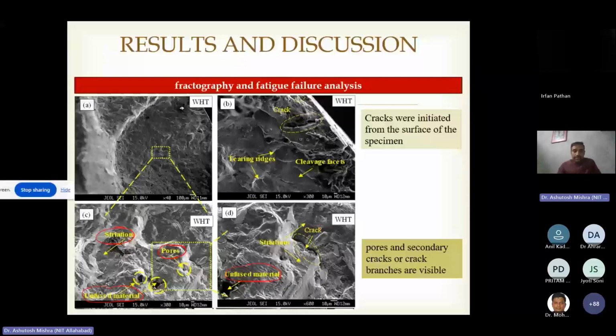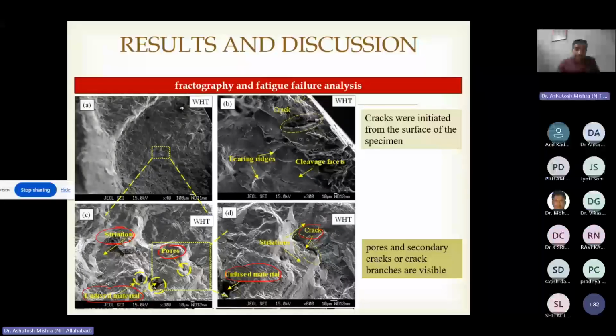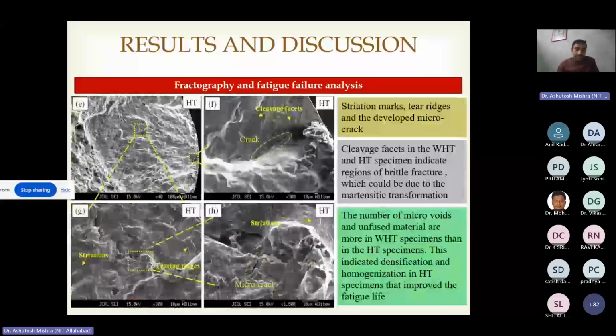Now, for crack initiation in this particular heat treatment, we see intermediary cracks, what we call crack branches, here. However, at the surface also we can see cracks, and for the WHT specimen, we can see cracks at the exterior part of the part. However, internal cracks are seen in the heat treated part. These internal cracks are of very small dimension, that is, we call them micro cracks.